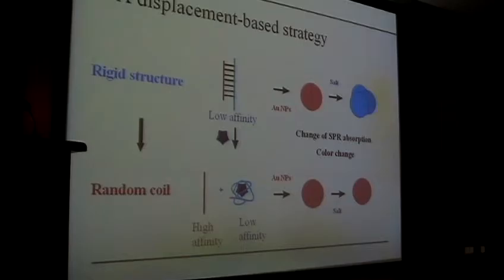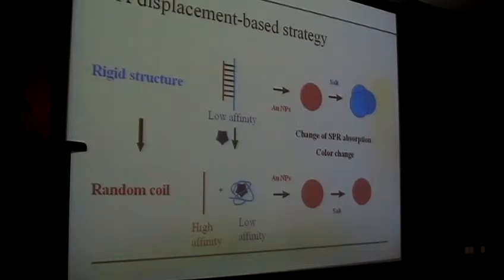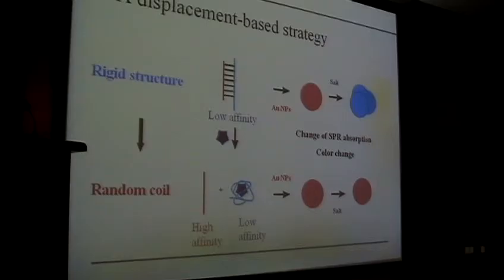There is a displacement-based strategy. We first hybridize the aptamer with its complementary sequence — not fully complementary; the complementary strand is a little shorter than the aptamer. In the presence of the target, it will displace this complementary sequence and release it into solution. This released single strand can bind to the gold nanoparticles, while the aptamer-target complex cannot, and the concentration of the released strand equals the target concentration.